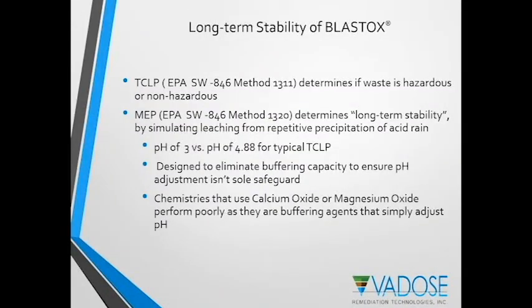Some additional testing has been done to demonstrate long-term stability of Blastox. We've talked about TCLP for characterizing the waste, and the MEP method for long-term stability. This method uses an acid with a pH of 3 versus 4.88 for a typical TCLP test. And as I described, it's an additional 9 sequential cycles of extractions.